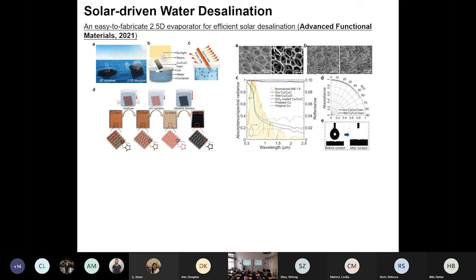And also this material itself is porous. It has micropores automatically. We studied the different pore size effect and also the porosity effect in this project. I want to show you. So we are able to achieve really nice water absorption and water evaporation performance through this project.